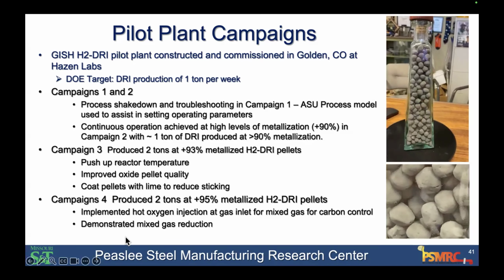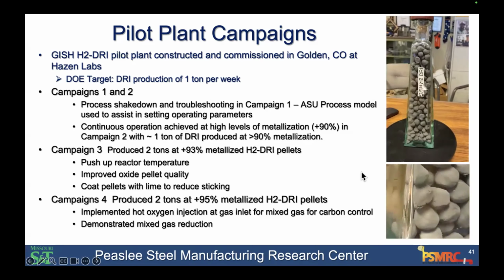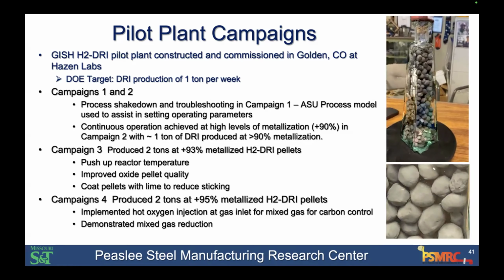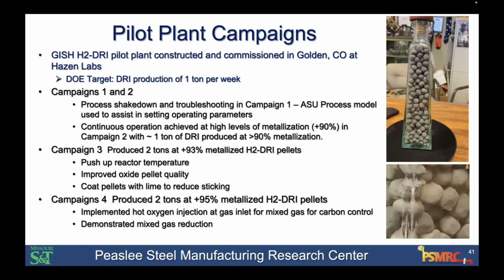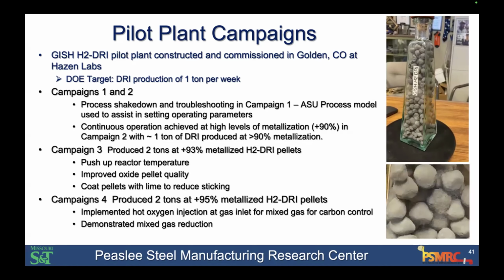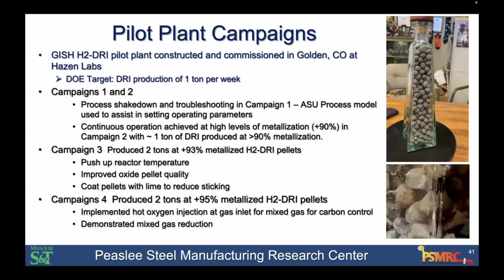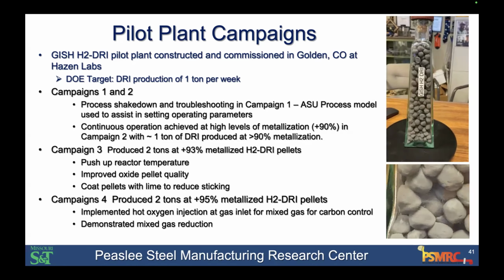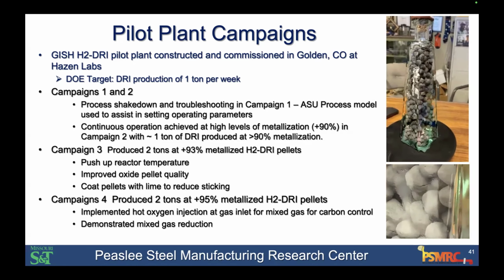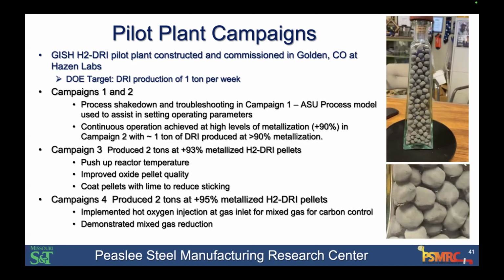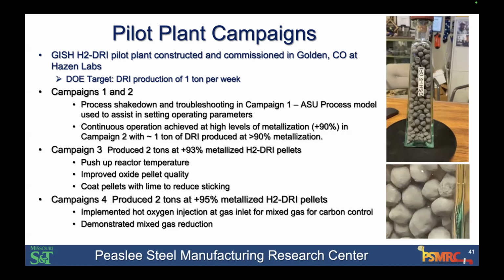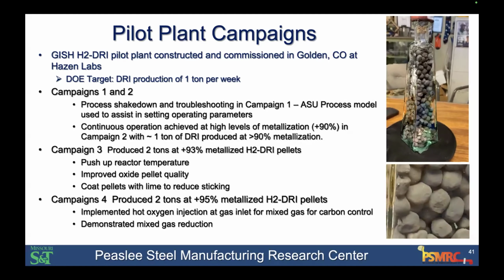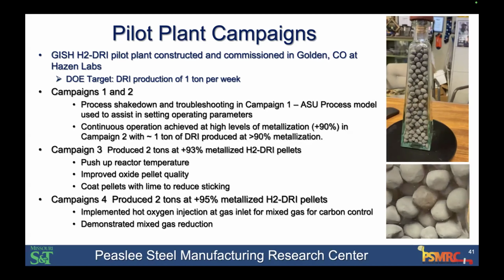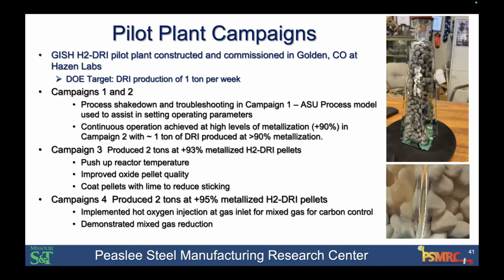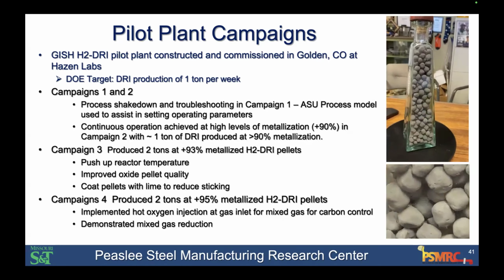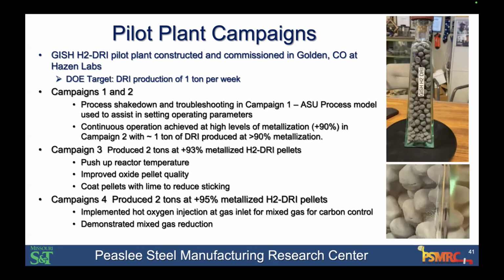We've actually operated these plants in 4 campaigns. Each campaign operates for about 1 week. And we have done pure hydrogen in various configurations, and then hydrogen and natural gas as well. And the pilot plant trials were totally successful. I will tell you that we early on had some issues. The very first trial, we actually had very cold weather in Golden, Colorado, and the temperatures were so low that we froze the water recycling system. And so we didn't get as high metallization and hydrogen utilization as we hoped.